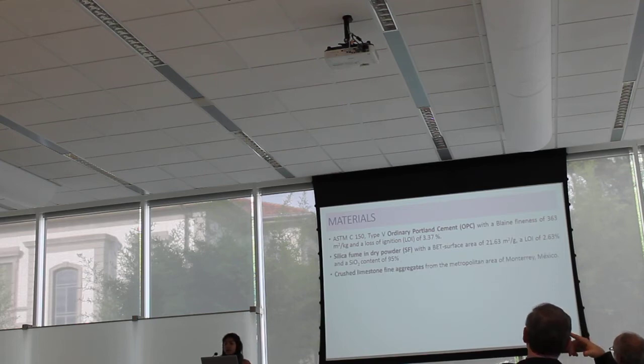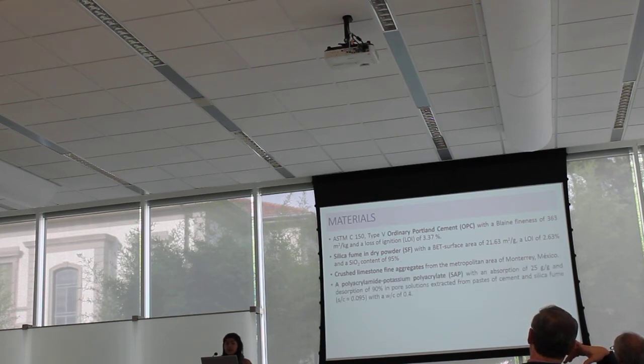The materials are an OPC, or ordinary type 5, meaning low content of C3A, silica fume in dry powder, crushed limestone fine aggregates from Monterrey, Mexico, and the SAP used is a polyacrylamide potassium polyacrylate with absorption of 25 grams per gram of water and desorption of 30% in pore solution extracted from pastes of cement and silica fume. Also a superplasticizer, a corrosion inhibitor admixture based on calcium nitrate, and a shrinkage reduction admixture.